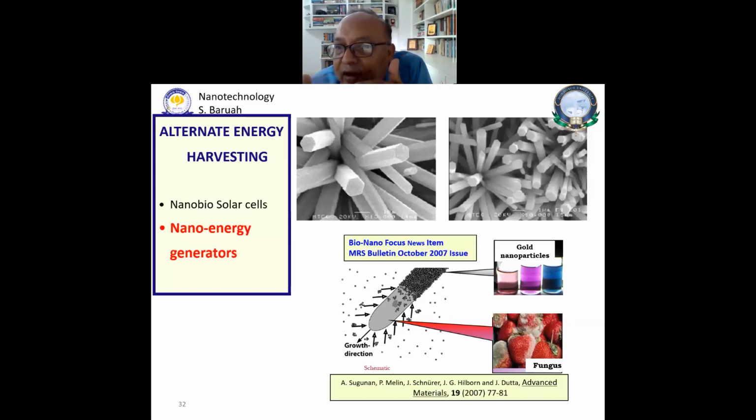Well, that led to a series of studies. It was a lot of excitement. My boss got so excited that he actually sent the student to Sweden just to do some studies on this. Finally, we found out that it was actually a fungus. Whatever chemicals he was using, fungus started growing on them. As the fungus grew, you see here, I've drawn this picture, it started pulling the gold nanoparticles to its surface. All this gold is coming and sitting here. That's why I was seeing the color getting lighter and lighter, because the gold was being removed from the water and sitting on the fungus.